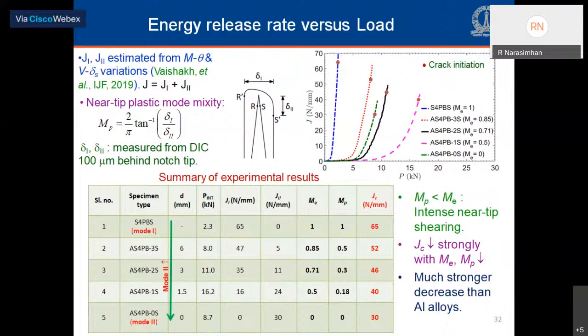So this slide shows the energy release rate versus the load. We computed the total energy release rate by taking the mode 1 and mode 2 contributions, using the moment versus the specimen rotation and the shear force versus the notch mouth sliding displacements, using a procedure which we derived in a paper in International Journal of Fracture last year. And the total energy release rate is plotted against load on the right side.